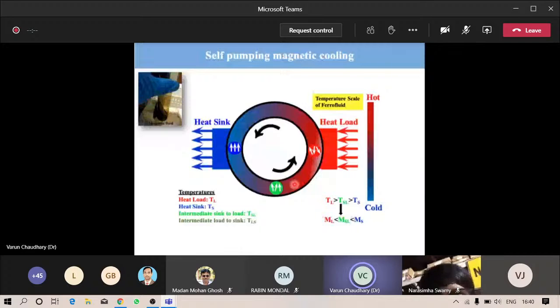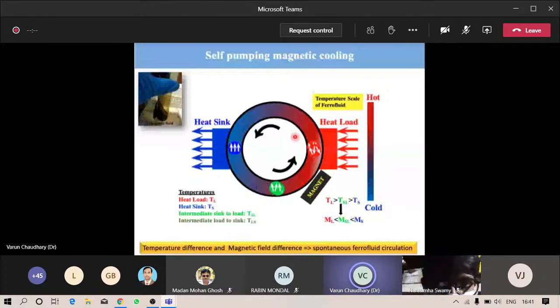Here you will see that, let's say this is the cold ferrofluid here, and this is the heat load and heat sink, and because of this heat load, the ferrofluid becomes hot, and when we apply the magnetic field, the cold ferrofluid is attracted by the magnet. At the same time, the hot ferrofluid doesn't have any interaction with the magnet because, you know, after a certain temperature it goes to its Curie temperature. So now, because of this thermomagnetic effect, it circulates spontaneously. So using this temperature difference and magnetic field difference, the ferrofluid circulates.